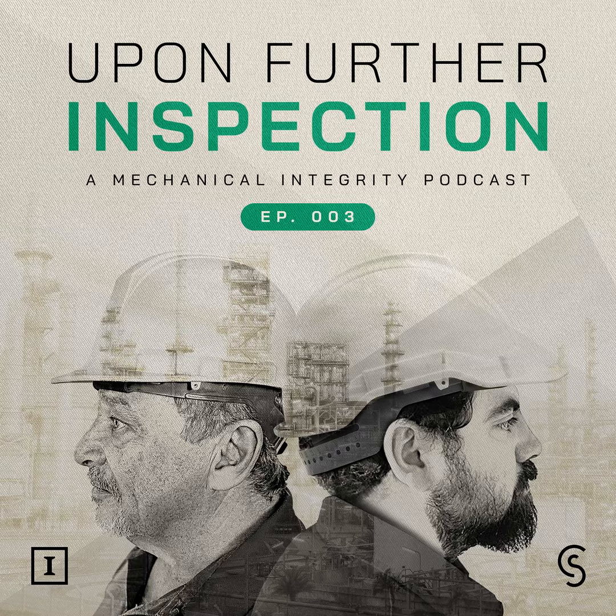Right. The cracking is best defined if it's transverse to the incident angle of the UT probe. So with 4 on there, when we're scanning along and that raster arm's going like this with 4 probes, and you can imagine you got those fillet welds on the inside, we're getting great coverage for cracking, like toe cracking coming out of the fillet welds from HIC-SOHIC. And we actually used to do those on PSA vessels too. Because their bed supports could have cracking if the fillet welds weren't really smooth.